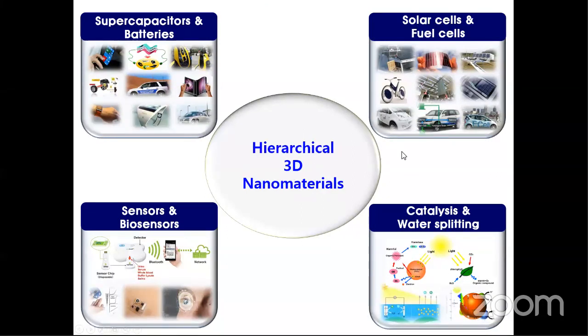That material should have hierarchical architectures. In order to get hierarchical architectures, we need to optimize the compositions of the initial precursors. For example, you can use bimetallic systems. We need to tune the mass ratio of the two metals, and you need to tune the mass ratio of the active support also. That is also one of the great issues for developing hierarchical 3D nanostructure materials.